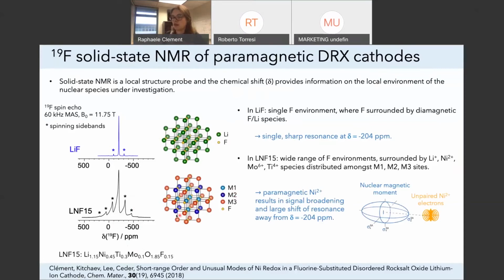And the way you need to understand these spectra is by understanding that the paramagnetic nickel ion, which is the only paramagnetic species in this material, will result in signal broadening and a large shift of the resonance away from the position of this resonance in LiF, which is why we see this much broader signal here. The reason for this is that your nickel has unpaired electrons in its d orbitals, and these unpaired electrons have a spin which interacts with the spin of the nucleus species we're looking at.